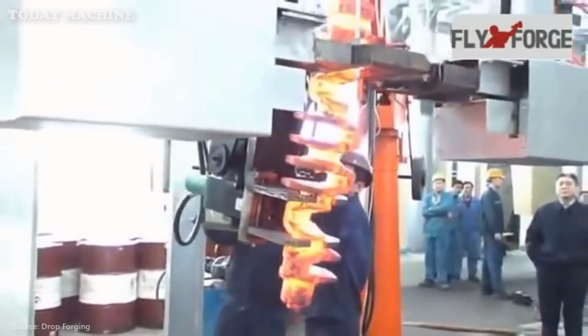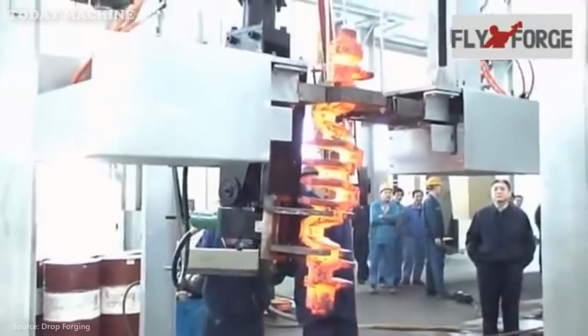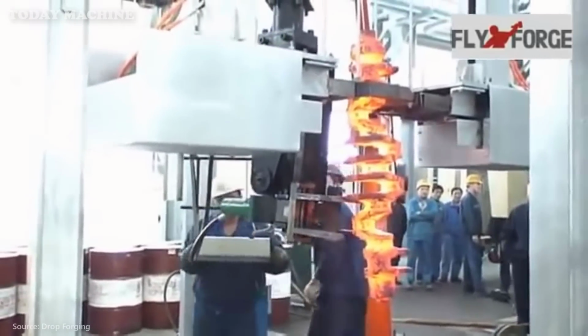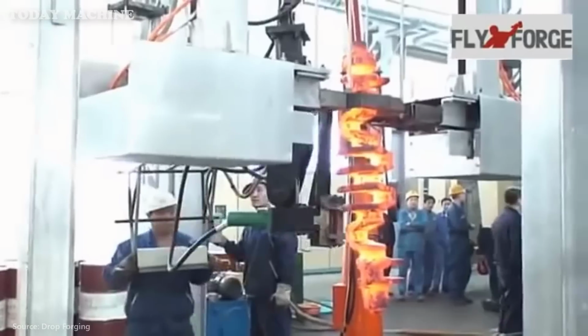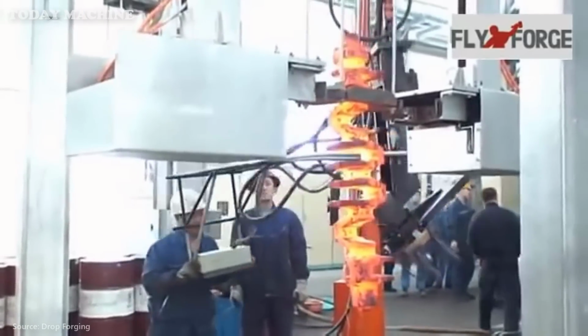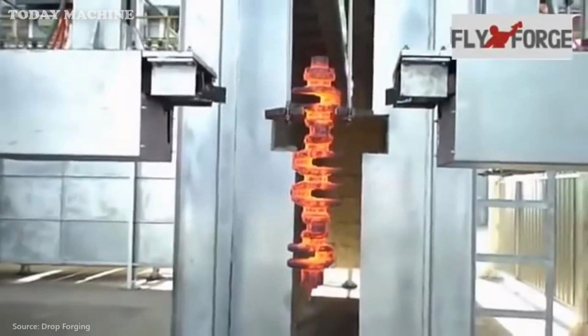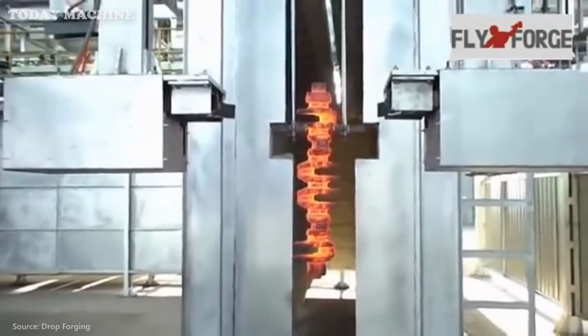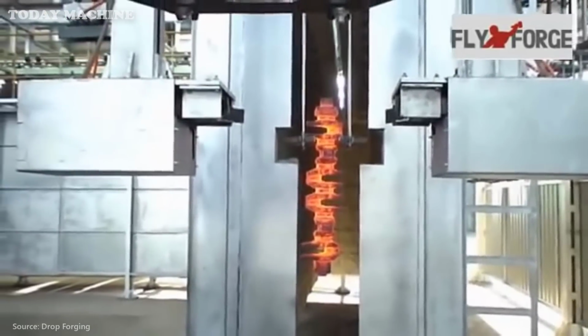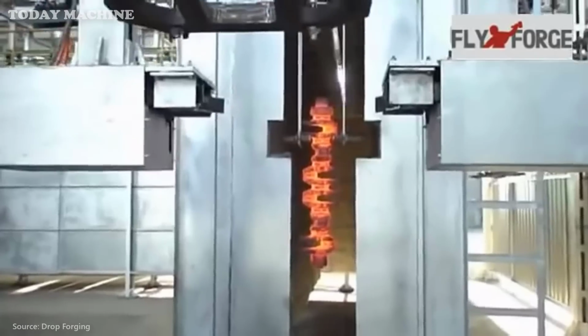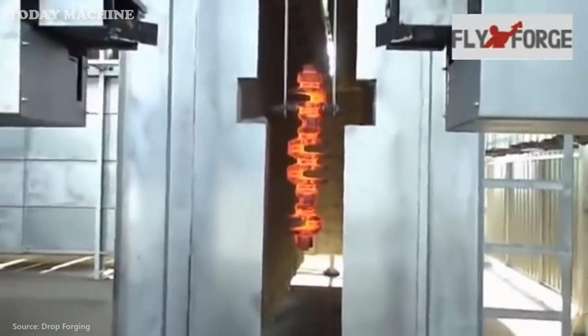Post-heat treatment, the crankshaft undergoes temperature suspension control, stress relief, and shot peening to improve fatigue strength. Flaw detection ensures there are no surface or internal defects. Anti-rust treatment is applied, followed by rigorous inspections to ensure quality compliance.